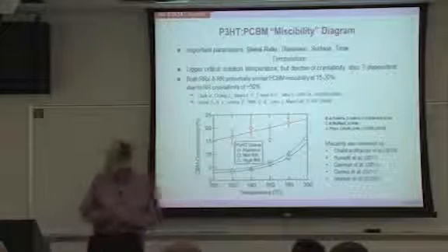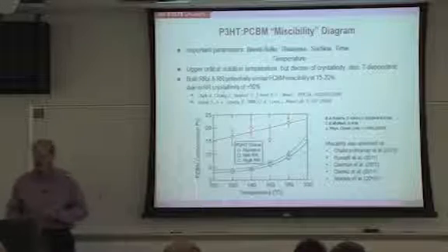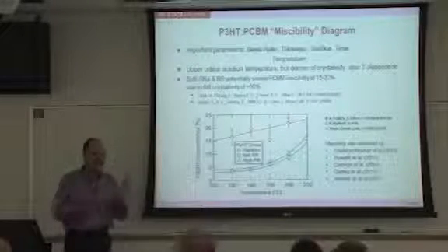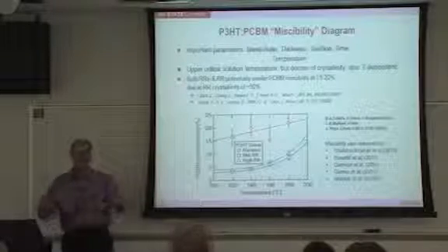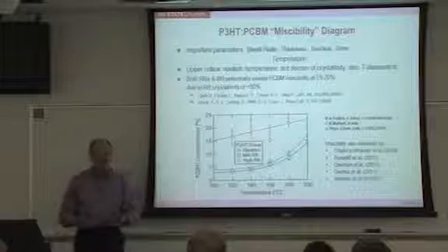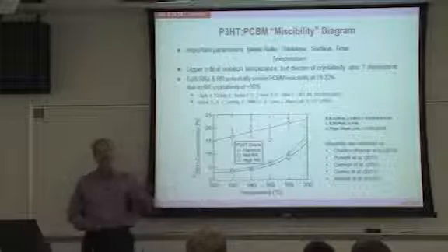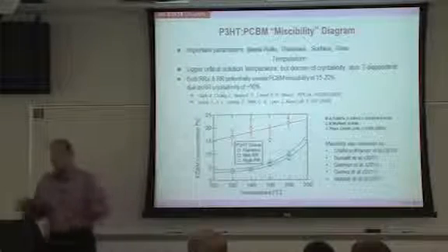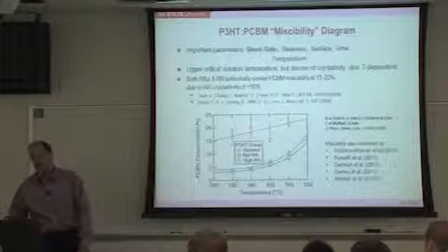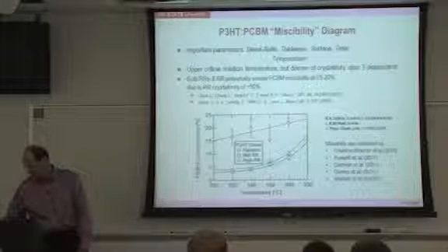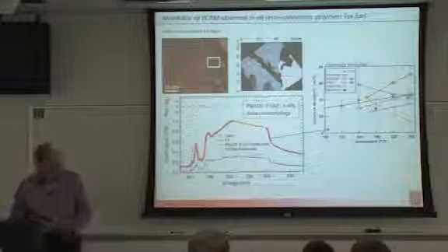Oh, okay, I see. So it's an average. Right. It's an average of both, because I don't have the spatial resolution in this measurement to differentiate the two. I could calculate out the crystalline fraction if I do pole figure measurements on the materials with X-rays. But we didn't go to that length in this particular system.